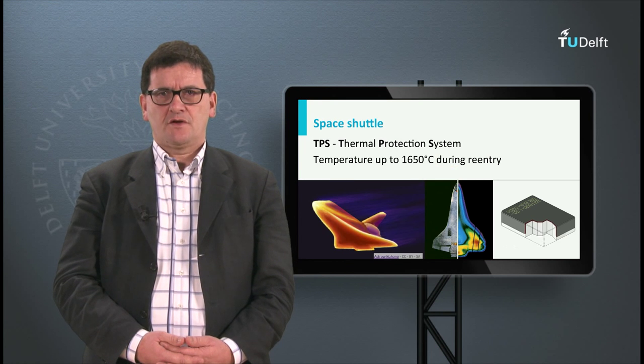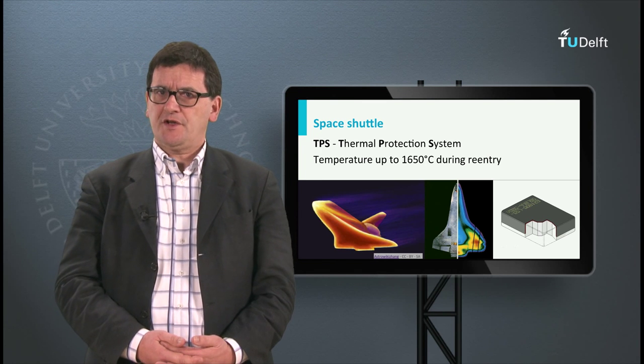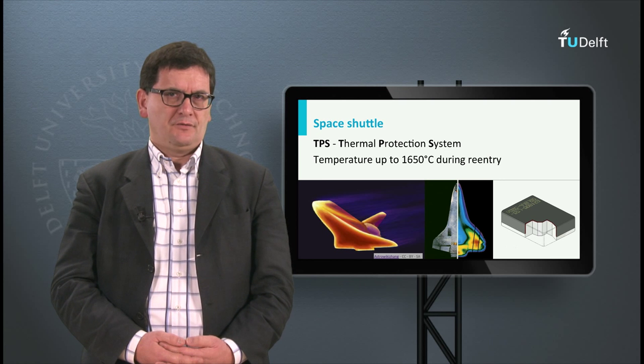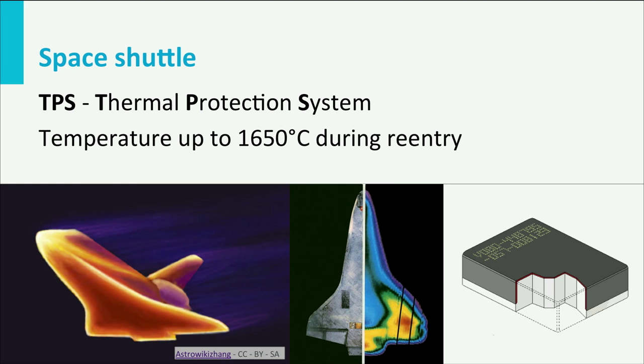The space shuttle used other materials to cope with the high temperatures. Its thermal protection system consisted of special carbon-carbon composites, special tiles and heat blankets. Each area had its own material. The hotter sections — the nose and the leading edges — were made of carbon-carbon composite, a hard but brittle material that can cope with temperatures exceeding 1650 degrees Celsius. However, the brittle nature of the material also took its toll when the shuttle Columbia disintegrated during re-entry because the leading edge was damaged.